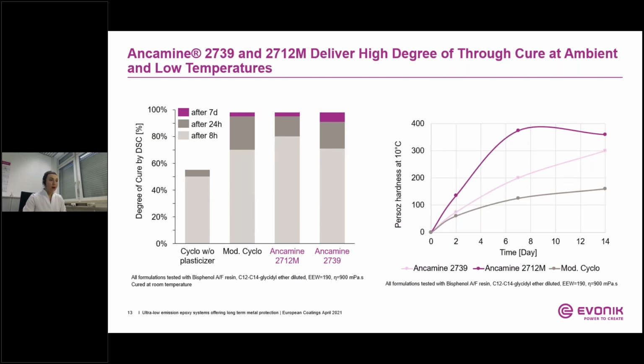Ancamine 2739 and Ancamine 2712M deliver a high degree of through cure at ambient and low temperature. To ensure a through cure without vitrification of the cross-linking reaction, the degree of curing over time was investigated here by DSC. The data has been obtained after allowing the clear coats to cure for 8 hours, 24 hours, and 7 days. The figure on the left-hand side illustrates the degree of cure. The results show that Ancamine 2712M and 2739 exhibit rapid conversion with epoxy resin to almost full cure at ambient conditions within 7 days, without the need for a high level of plasticizer.